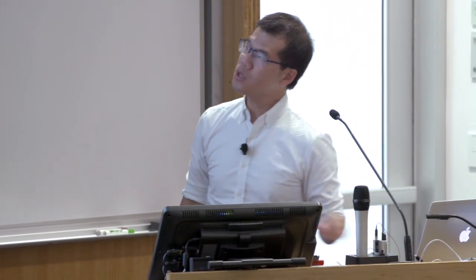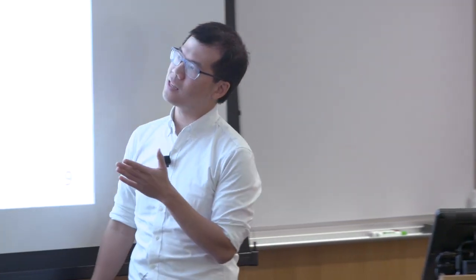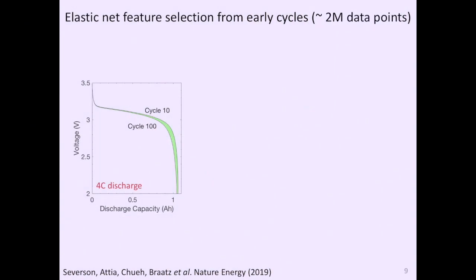And what we thought to do is, rather than just using this capacity curve, each data point here also contains about 10,000 data points on voltage and current and temperature versus time. So why don't we look at one level deeper? And when we do that, we're able now to follow basically not just the evolution of the battery capacity, so that's the runtime of the battery, but also the subtle change in the voltage of the battery as a function of time for each charge and discharge cycle you do, and that's plotted there. The green is the difference between two cycles, in this case between cycle 10 and 100.